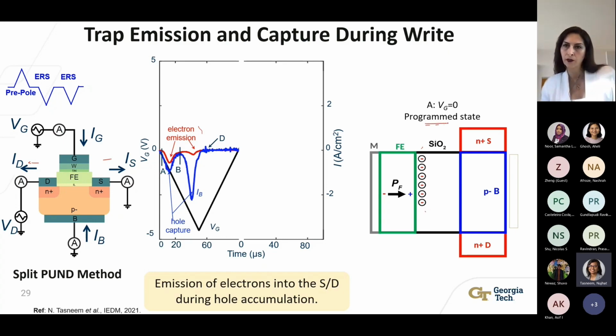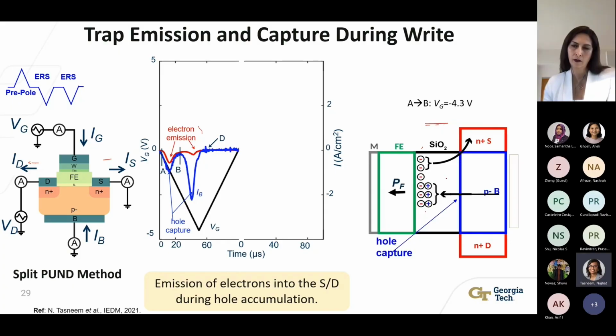Now, when we start erasing this programmed state by applying a negative erase pulse, then this trapped electron starts getting emitted. A portion of these emitted electrons goes to the channel, which has a lot of holes, and gets recombined there. But the main point here is that the amount of emitted electrons is so large that even after recombination, a significant portion of it gets collected by source and drain. And this is what we are actually measuring in the split PUND technique, and is shown by this red curve over here. So the main point here is that there is an emission of electrons when the device is in hole accumulation, and a major portion of it gets collected by source and drain, which we can measure using the split PUND technique.